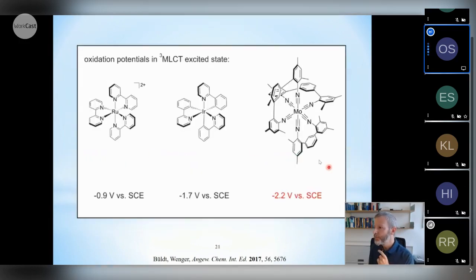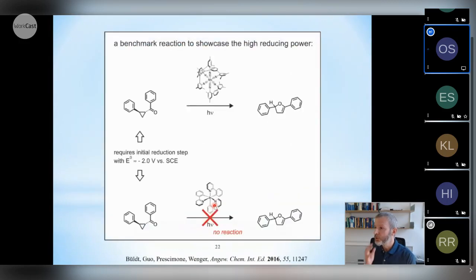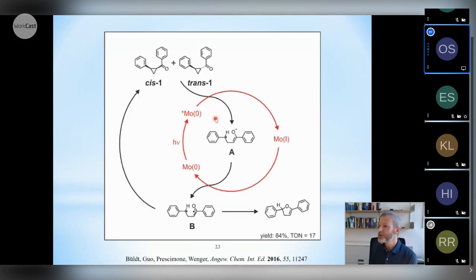What's different, however, to Rubpy is the reducing ability of these compounds in their electronically excited MLCT states. This is a very strong photoreductant, far stronger even than the commercial iridium ppy photoreductant that is used a lot by the organic photoredox catalysis community. And Laura exploited this, along with Xingwei Guo, in a rearrangement reaction, which requires an initial reduction step with a very negative potential, around -2 volts versus SCE. So the iridium standard catalyst cannot catalyze this reaction. It's not reducing enough.